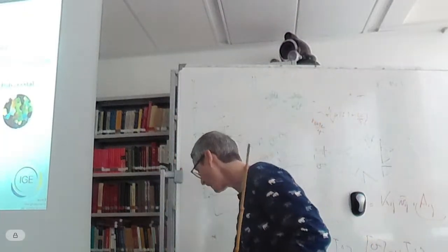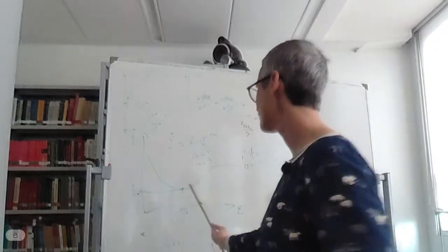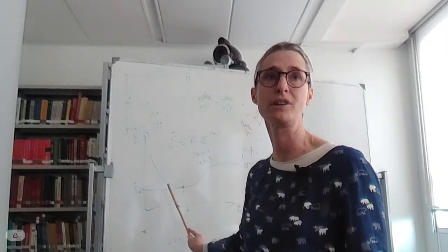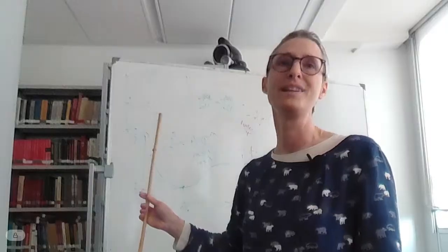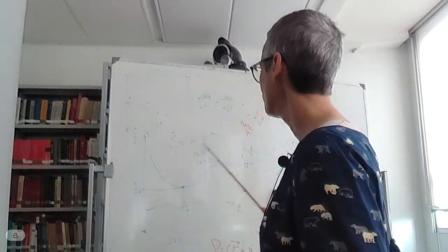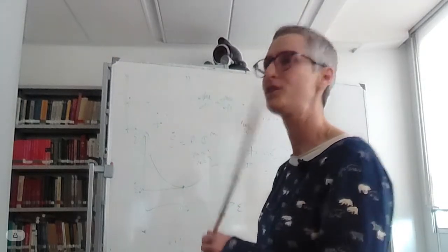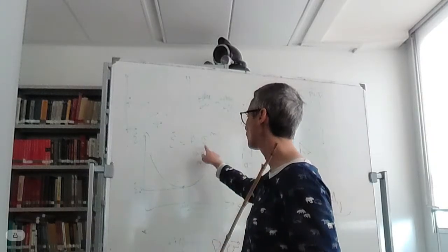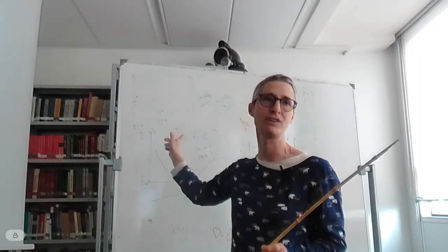And so it's somehow an easy step, an easy way to say, okay, we're considering that we have here what should be a stationary creep, and we take the condition of stationary. We know from the lab that it's not stationary, because right after we have dynamic crystallization, and then this law does not really hold anymore. But that's the best we can do right now. And it is in this kind of law that we are trying to put some anisotropy by reshaping all that, so that it's not only a law that relates to temperature and stress, but also crystallographic orientation.